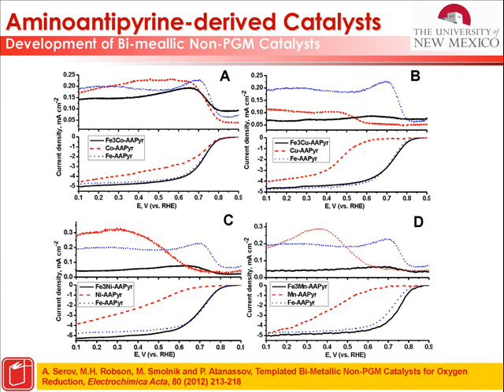So now here comes the non-traditional thinking. Every chemist thinks that the species have to ligand the iron in a solution in order to make a good catalyst. That's why our first choice was a very cheap material with a lot of nitrogen that makes a fantastic red complex with iron when you put it in solution. And you say, great, it will make a great catalyst. Then you say, okay, does it really need it to make a ligand? Maybe the pyrolytic chemistry that happens after 700 degrees C doesn't require that complex formation. Then we put in another amine that we specifically selected not to make a complex with iron. And we make the impregnation with that. The catalyst was comparable and in some cases even better.